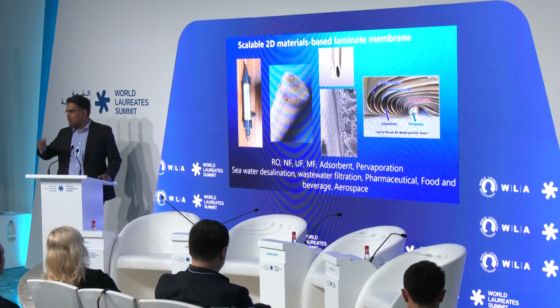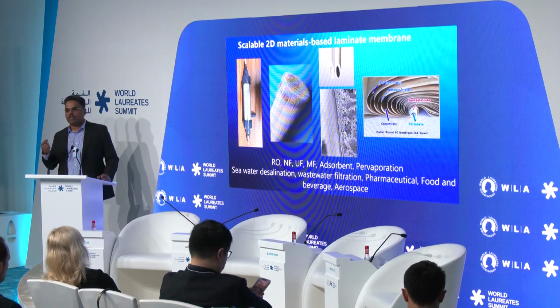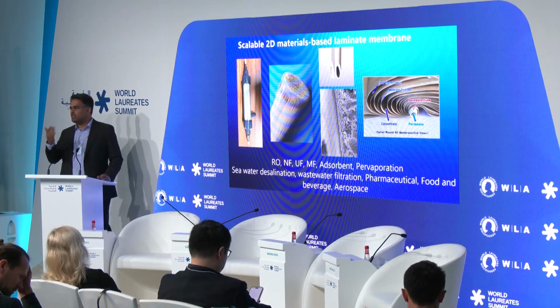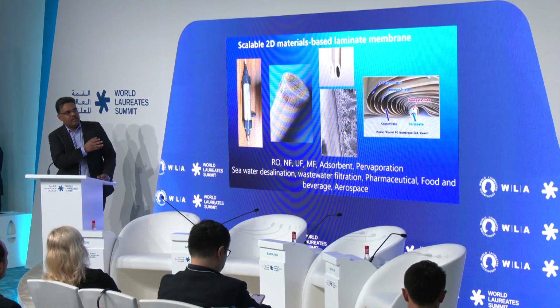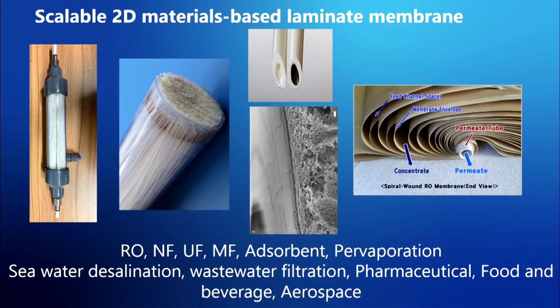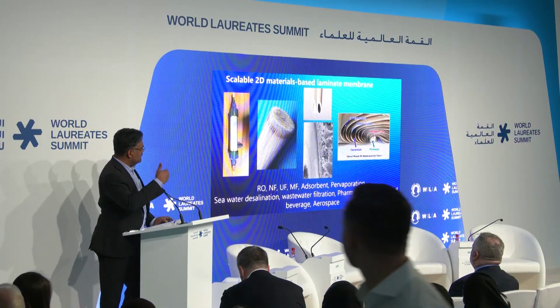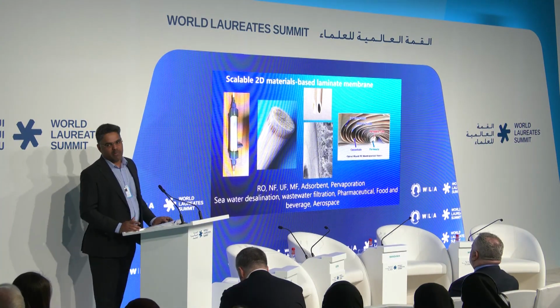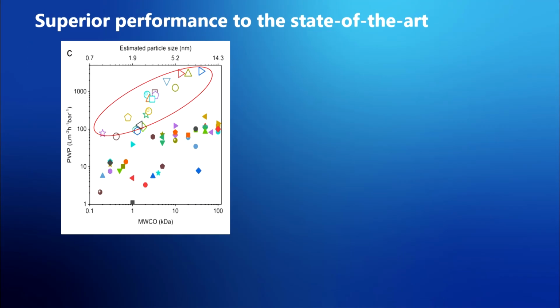Basically you take a polymer tube, then you modify or coat it with any of these 2D materials. The coating can be inside or outside. What you see in the middle picture is a scanning electron microscope image. The active layer, which is around tens of nanometers to hundreds of nanometers, is tunable, and that gives all the selectivity to the membrane, and the substrate, the bottom layer, is a porous polymer. The same thing can also be applied to the desalination membrane, which is not a hollow fiber but a spiral wound membrane. You just make a piece of paper and then spiral it to make a large area membrane.